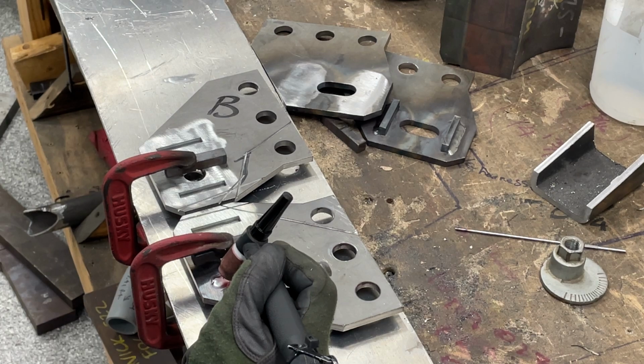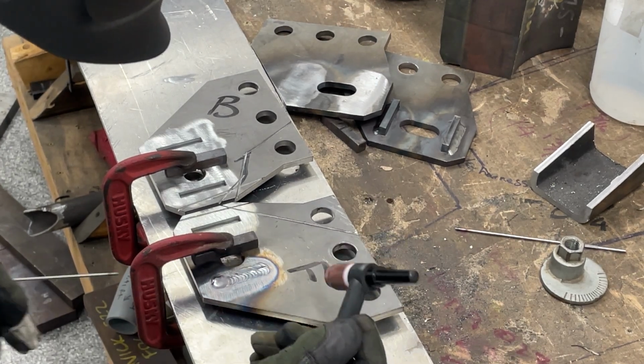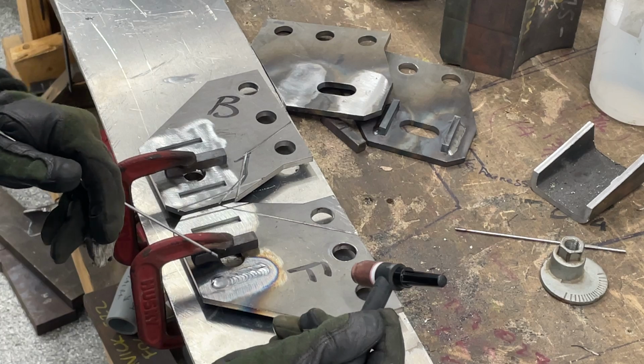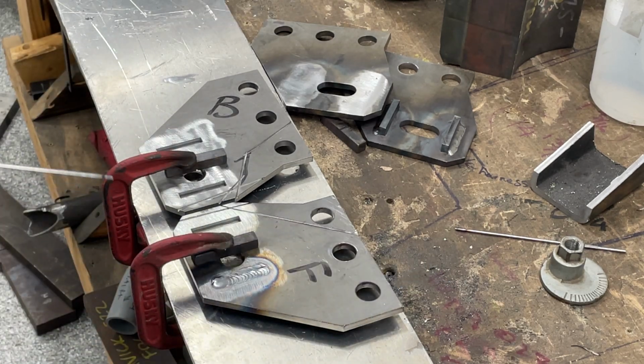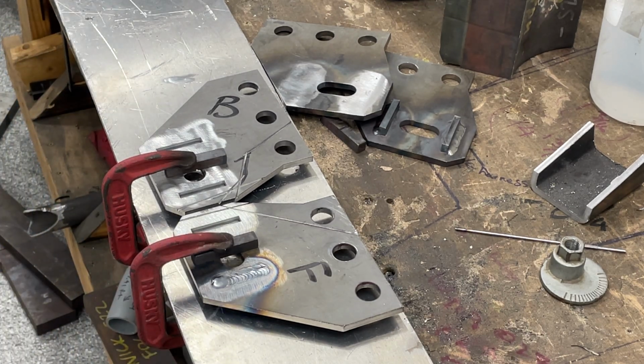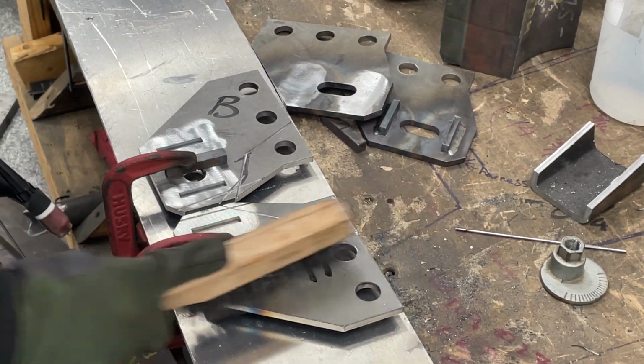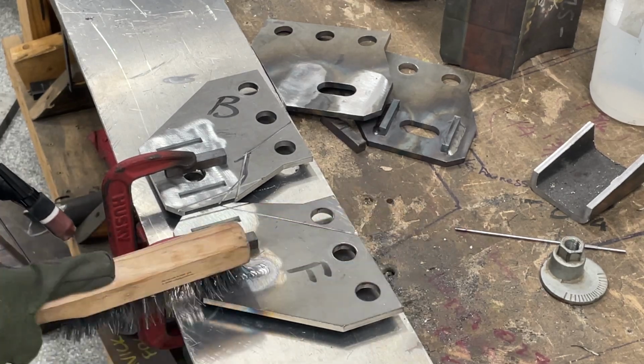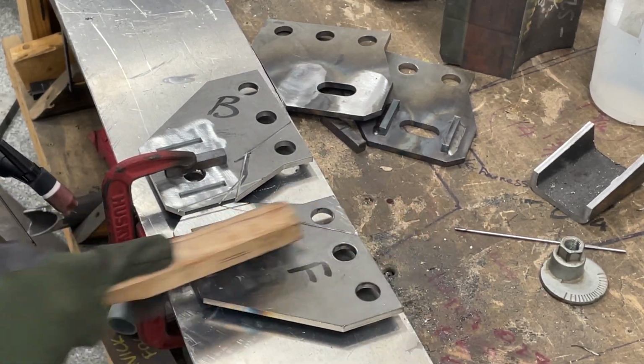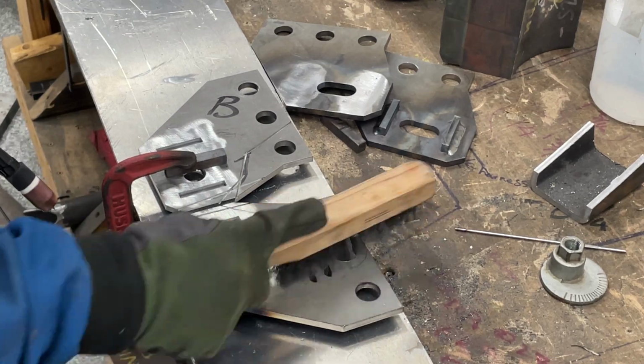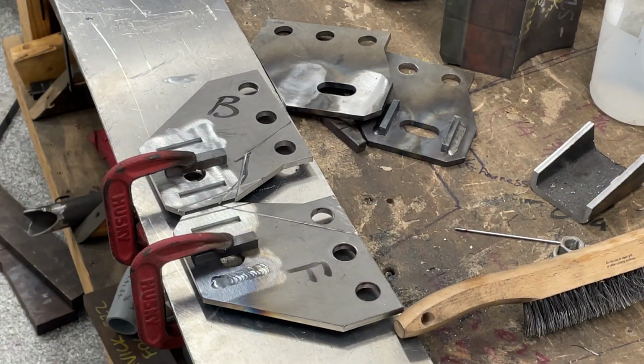The slower you stop your arc, the less you will need to grind your starts and stops. You can see how that start and stop has no solidification crack at all. If you are in a regular manufacturing shop where you're worried about pass-fail criteria, you'll probably be grinding those starts and stops. Okay, need a wire brush. Let's check to make sure that we don't have any silica beads or silicon islands up there. Okay, it's looking very pretty, very nice.